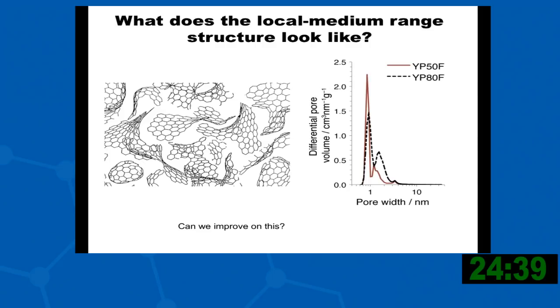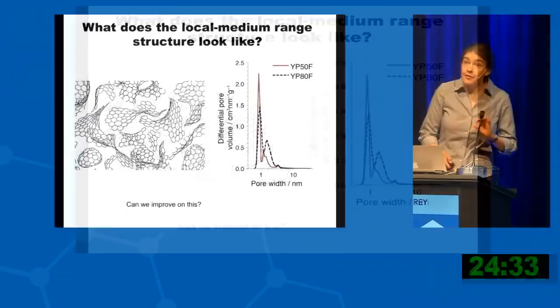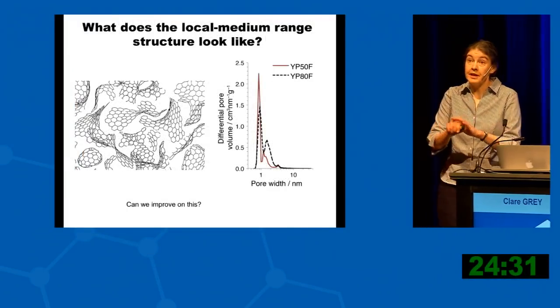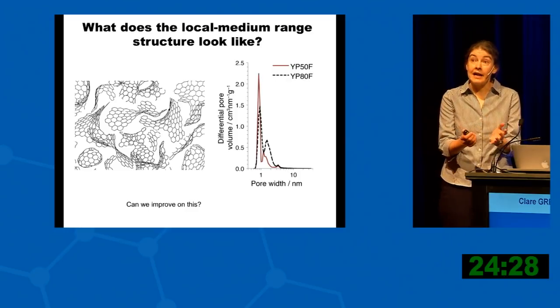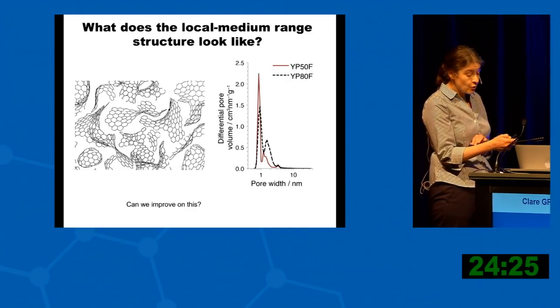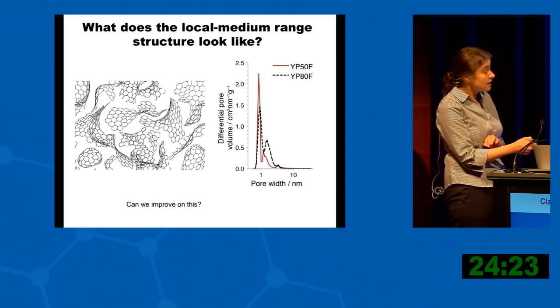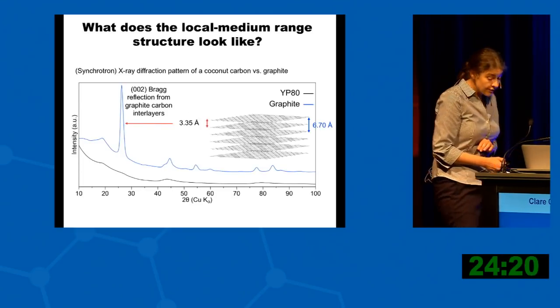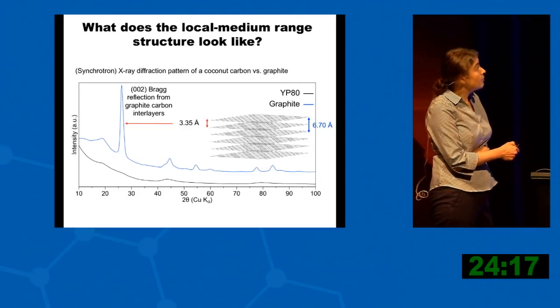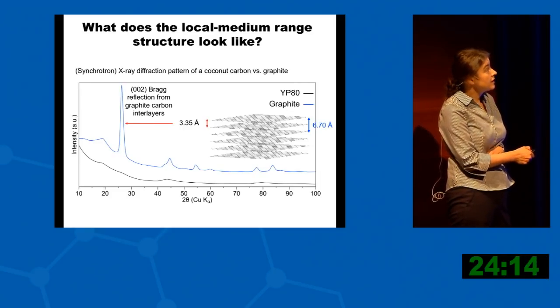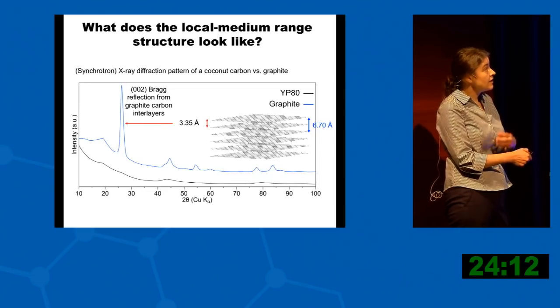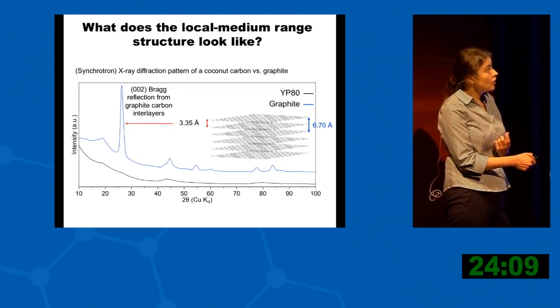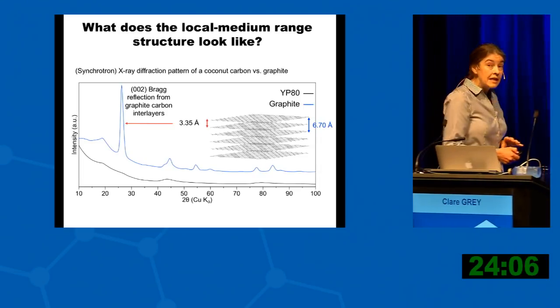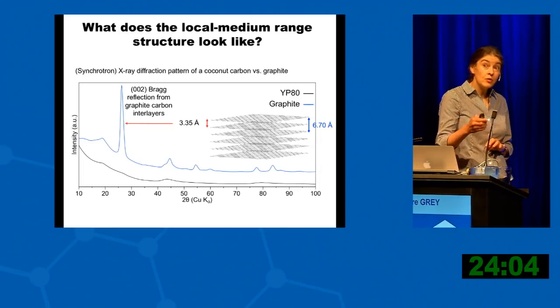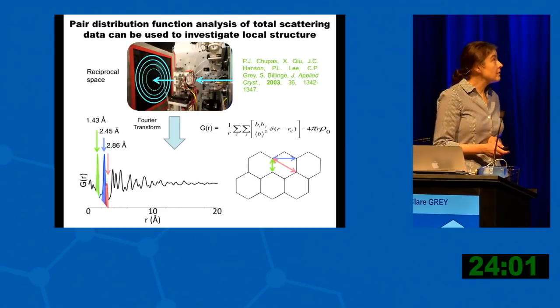So these are two commercial hard carbons, and they're largely optimized to give pore widths that are about a nanometer. And the reason why that's important is that's about the size of a solvated anion or cation, so you optimize the storage of the anions and cations inside the pores. So what does a diffraction pattern of one of these look like? So in blue is a typical diffraction pattern of a graphite, and down below is a hard carbon, and you can see there's no long-range order, but there's still nonetheless weak intensity from the total scattering or the diffuse scattering, which indicates there must be short to medium range ordering.